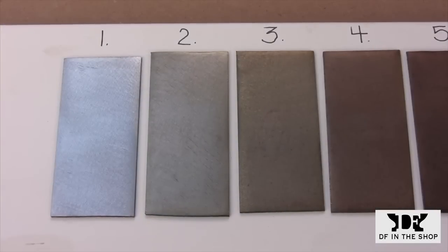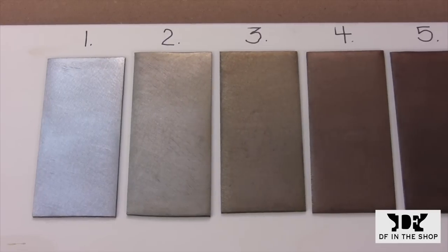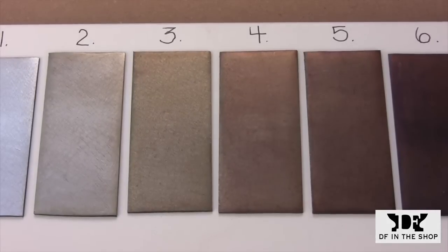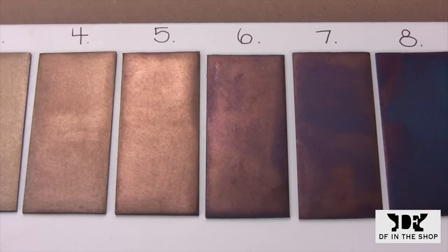So at the low end of the scale, you have sample number 1, and this is a polished piece of steel with no heat applied to it. So this is what you're starting with. Number 2 is the first visible color that you see, and it's usually referred to as a light straw. Number 3 is a few degrees hotter, and it's usually described as a dark straw. In number 4, the straw color transitions into more of a bronze color. Number 5 is kind of hard to describe, but it's sort of a darker bronze. Sometimes it has reddish patches to it.